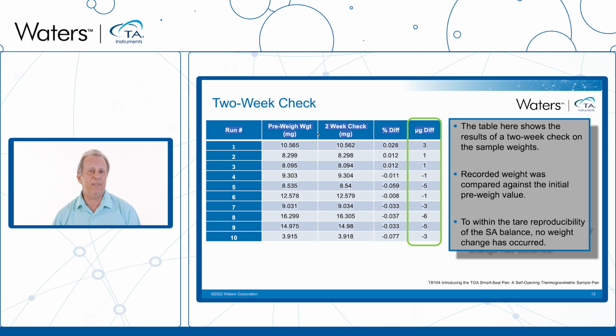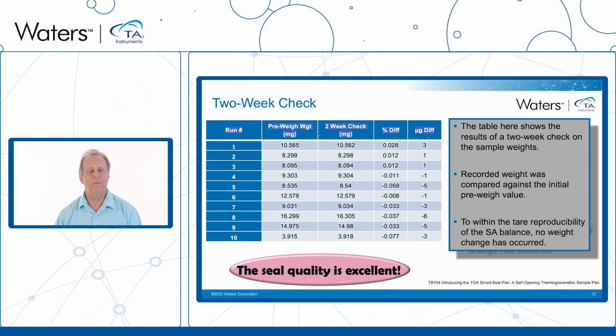For the Discovery TGA, the tare repeatability is plus or minus 5 micrograms, meaning that if you tare a pan and check its tare several times in a row, the tare value will be within plus or minus 5 micrograms. All of these samples fall within that. All of these samples show that they are perfectly hermetically sealed inside of these pans here. So the hermetic quality of these seals is actually quite good.